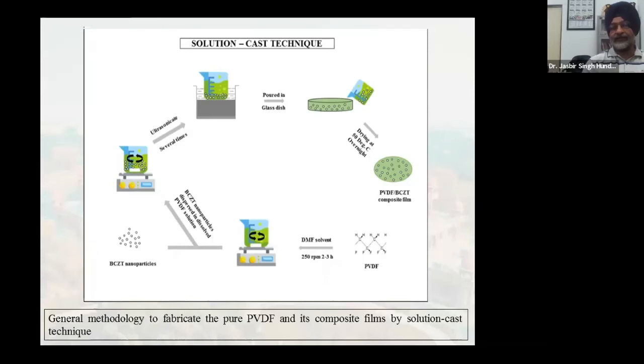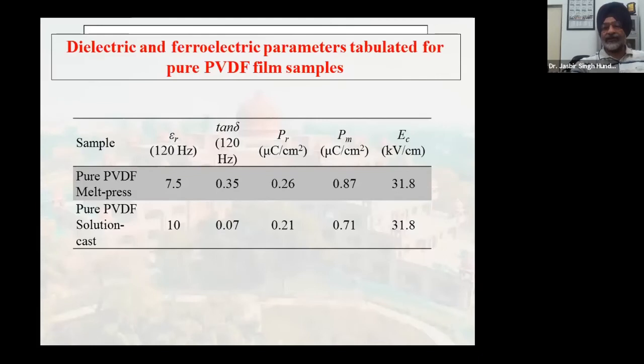In this case, we are using DMF solvent in which PVDF dissolves, and the BCZT nanoparticles are spread in the solvent. So you get a kind of suspension, right? And then you can spread it over a substrate and put that in a vacuum oven, so that slowly the solvent evaporates, leaving behind a film. But for styrene acrylonitrile, we used acetone for solvent cast films.